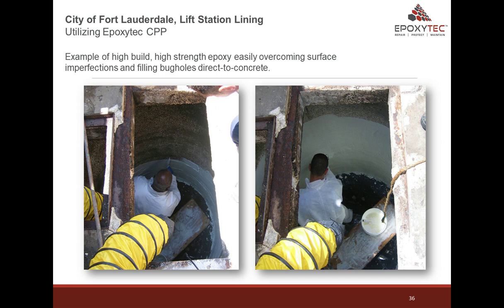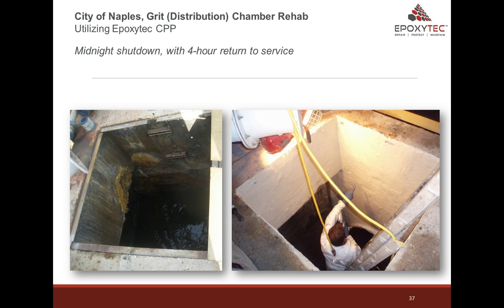The second picture, this is a City of Fort Lauderdale lift station lining, utilizing Epoxytec CPP Trowel Grade, an example of high build, high strength epoxy easily overcoming the surface imperfections and filling the bug holes direct to concrete. Look at this picture, the CSP is somewhere around 5. You can certainly see that the product is more than capable of bridging that type of profile as well as resurfacing and lining the substrate.